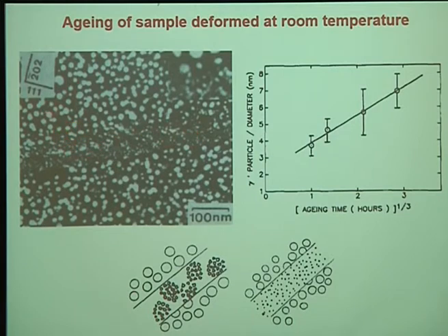So what did we do? We tried to study the kinetics of this as a function of time. This is what is being plotted, and then we try to see at zero time where it meets, whether it is below the critical size or not. On this basis, we could conclude that in some microstructures where the precipitate size is fine, and that has taken a large number of cycles, the precipitates have completely dissolved. In one where the size is large, we still are not able to see it, so they are remaining there. This was also published in Acta Materialia.